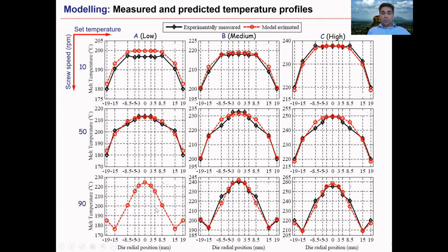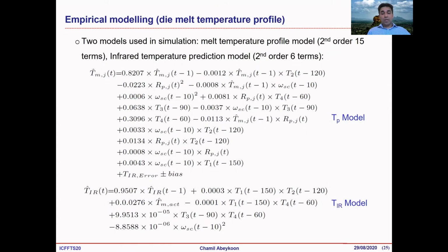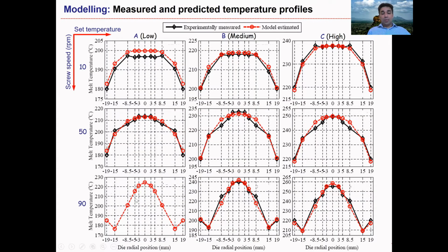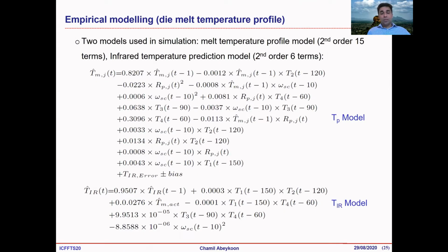Here you could see we don't have a black line, so we don't have experimental measurements because the sensor was broken. As I said, the thermocouple mesh is really fragile and can be broken in some situations. That is why it is not compatible with industrial settings yet. Now we have a model to replace the thermocouple mesh, and we want to extend this to be a soft sensor. These are the kinds of models that we developed.